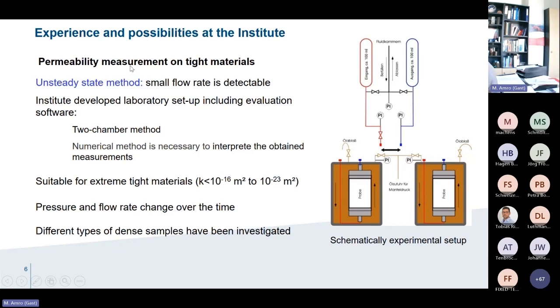But we deal with very tight systems. That means we have to consider a certain method to come up with the results as fast as possible. If we consider the steady state method, we will take a lot of time to get one measurement. For example, maybe 6 weeks or more than that, just to get one measurement of permeability. We decided to consider the unsteady state, which is a function of time. And within this method, we can identify very small flow rates and very small changes in the system.